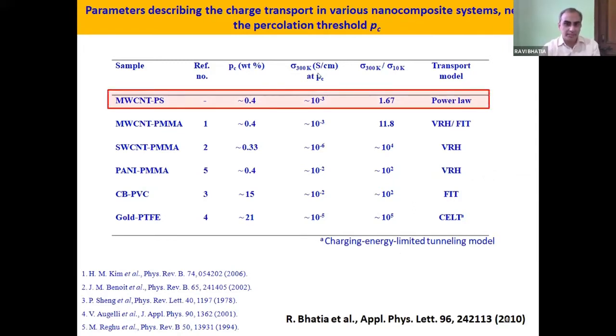For example, the room temperature conductivity of this particular sample, which was presented in the previous slides, is the same as our room temperature conductivity. Both achieve the percolation threshold at the same level, but the transport model for them is VRH or FIT, and for us it is power law behavior. So this is a significant study which shows that the quality of multi-wall carbon nanotube matters, and the homogeneous distribution of CNT matters, and the material processing as a whole is a very big area of research.